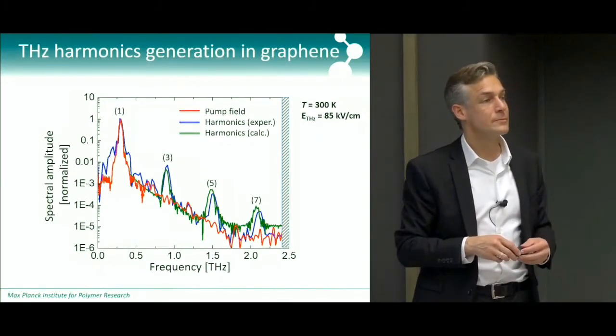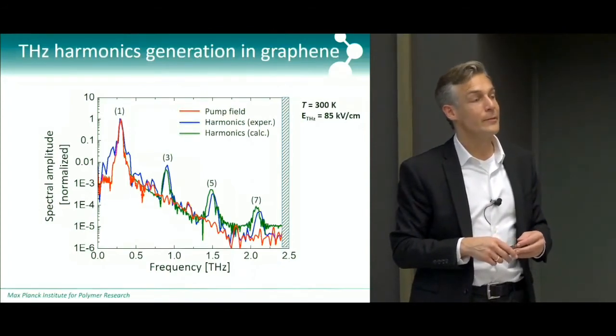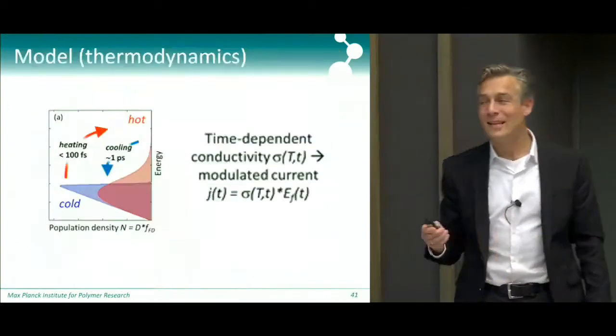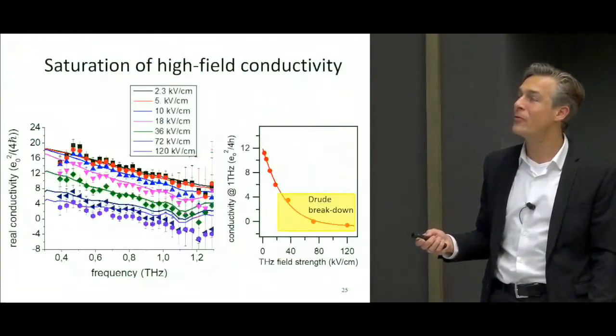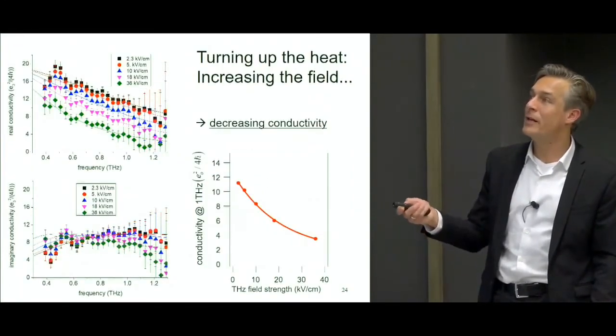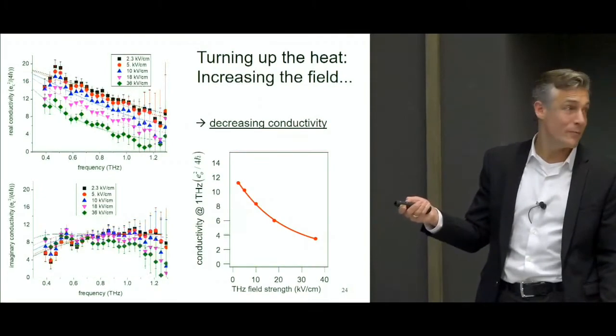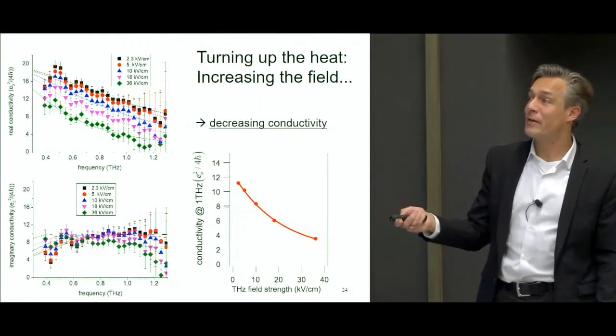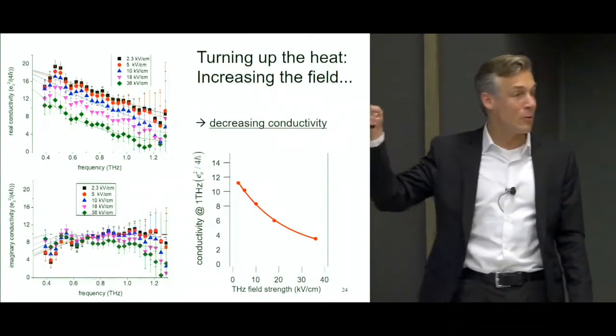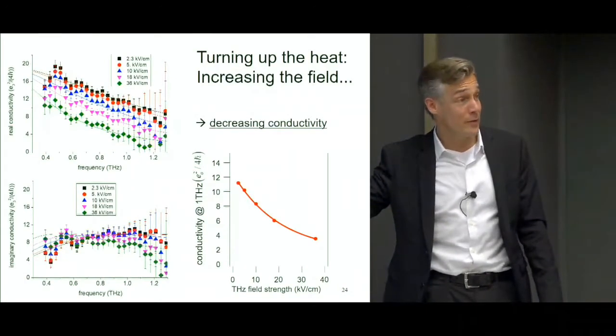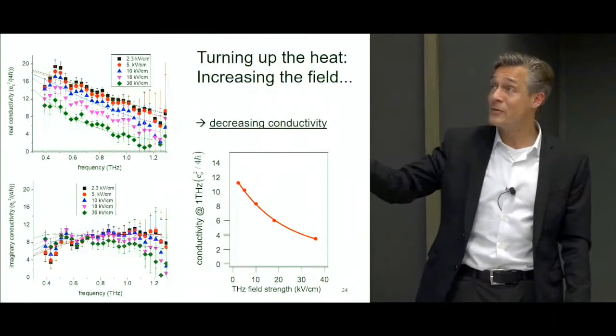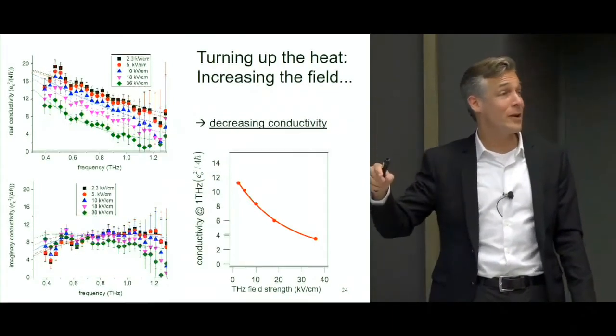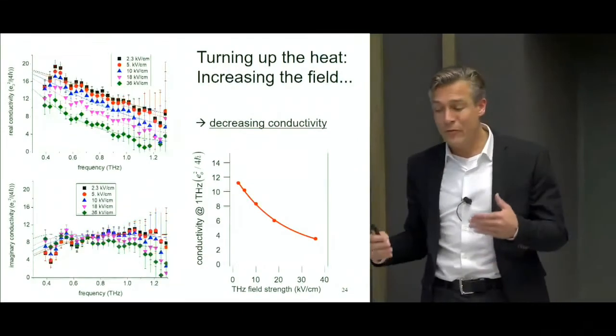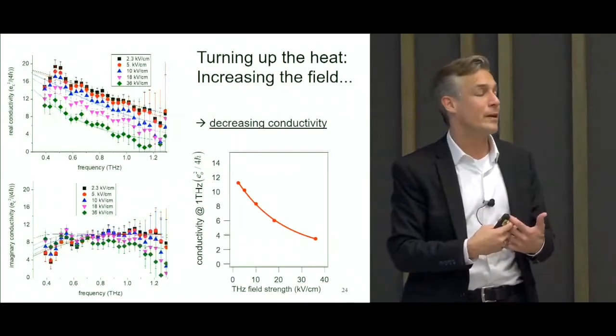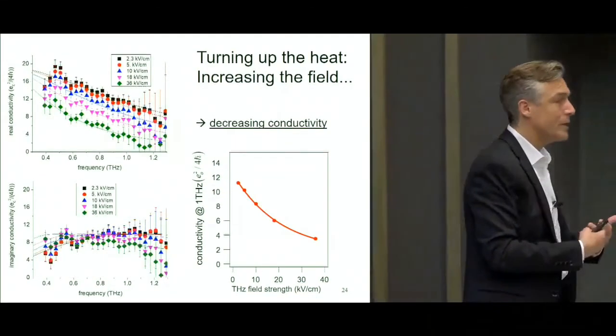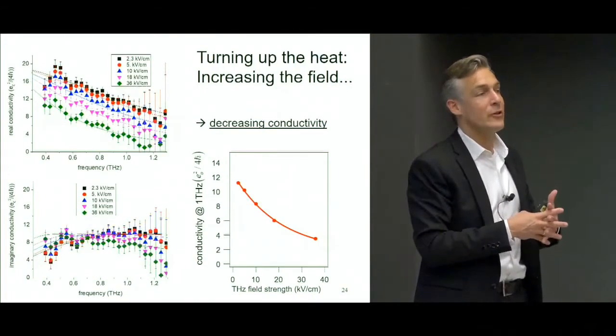You told us that when you heat up the electron bath, then the mobility decreases. Right. Why would it decrease if you don't have any phonon? Yeah, that's a very good question. So the weird thing is, as you see here, the conductivity goes down, right? And you see that this doesn't change so much, so the crossing point goes to lower frequency, which means longer scattering time. And so as you heat the electrons, the scattering time gets longer. And so there are different ways of explaining why that leads to a lower conductivity. In essence, it has to do with the very peculiar band structure of graphene.